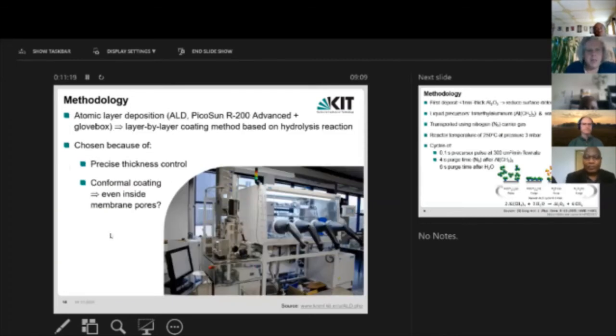Then we get down to some thin film deposition, something I love doing. So here we chose to use atomic layer deposition. In the system you can see here, from the Finnish company Picosun, the samples are loaded in through this glove box. We don't need the glove box in our application because our samples are air stable, but some of the other materials being handled here are not. So for those of you unfamiliar, atomic layer deposition is a layer by layer coating method based on a simple hydrolysis reaction. And we chose to use atomic layer deposition because you get very precise thickness control down to the angstrom level. And it is possible to achieve conformal coatings. So this means following the contours of your substrate. And thus for us, the challenge is that maybe we can even get the thin film deposition happening inside the membrane pores.